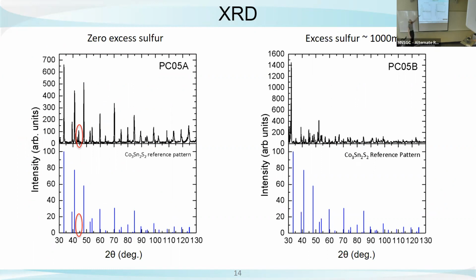As you can see with 0 excess sulfur, the reference pattern lines up exactly with our peaks, which is great. There were a couple that we couldn't identify. So it's nearly phase pure, which for us is good enough. And if you add extra sulfur, you can see that it kind of kills the growth and you have so many other materials within that sample. So we're using the one with 0 sulfur.